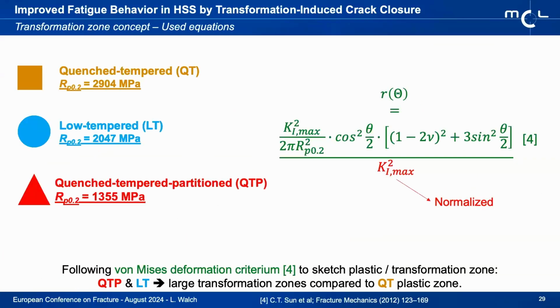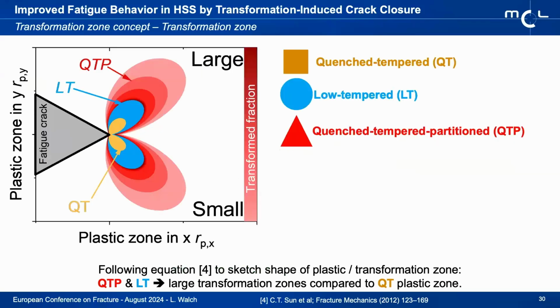Now, this is just a final interpretation of those fatigue results that we tried based on a simple transformation zone concept, here illustrated by the example of the von Mises deformation criterion. And if you look here, of course, based on the tensor of the stress strain behavior that you've seen before, the transformation zones or plastic zones differ quite significantly for each material state.